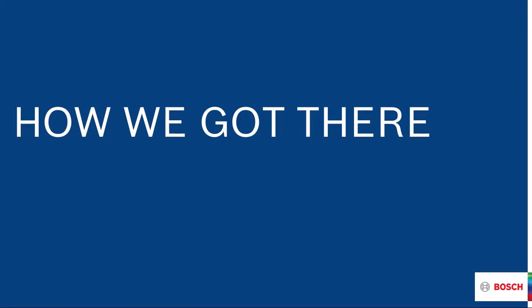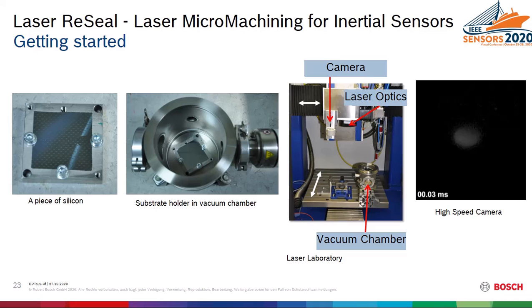So how did we get there? Well, we started with this very small chunk of silicon in a small vacuum chamber. The chamber was placed inside a laser chamber in our laser laboratory in Renningen. Because the vent holes are very tiny, we had to use camera systems in order to find the right spot. But we also used a high-speed camera system to analyze the melting and recasting behavior. On the right-hand side, you see a nice little video showing the process.